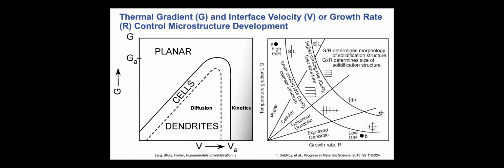I already showed this schematic here if you open a solidification textbook, and our early work was really this diffusion controlled regime where we're heat and solute transport dominated. That said, if you go to higher velocities, kinetics becomes important, where we lose local equilibrium at the solid-liquid interface. So kinetics becomes more important for scenarios, again, like welding or additive manufacturing of materials.